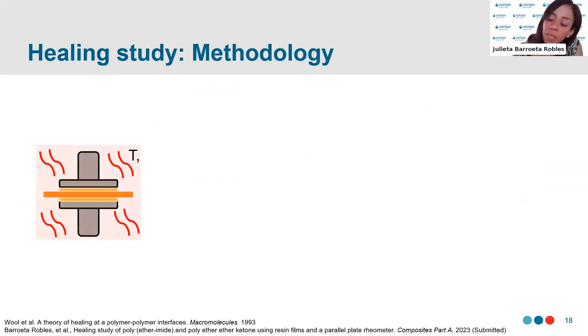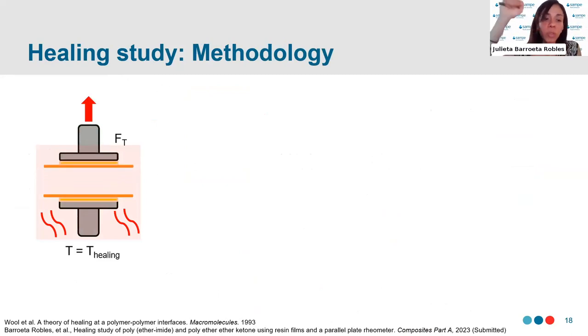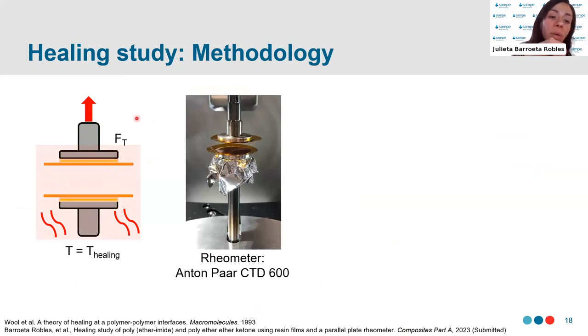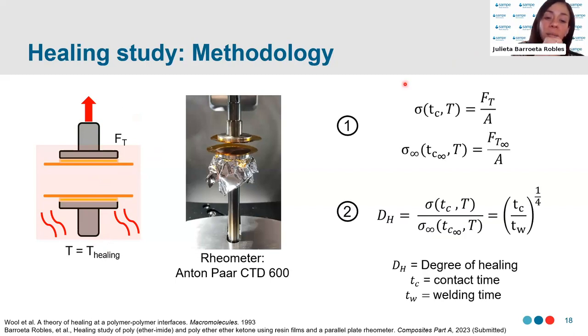Once this healing temperature was obtained, then a force of 30 newtons was applied, and this was kept at different contact times. And these contact times range from a few seconds up to 20 minutes. Once the desired contact time had elapsed, then the specimens were pulled, and the maximum force that was required to separate those specimens was recorded. Now, we have that force and we know the contact area between the polymer films. So then stress was able to be calculated. This was done at each contact time and temperature, and also at the maximum contact time for each temperature.